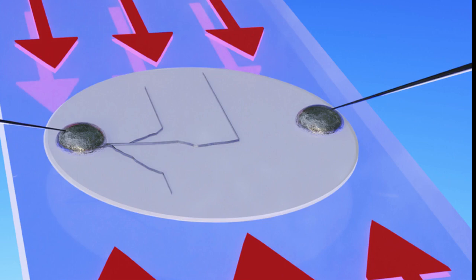In fact, a different kind of stress, called stack pressure, is often applied to battery cells, by essentially squeezing the material in the direction perpendicular to the battery's plates, somewhat like compressing a sandwich by putting a weight on top of it. It was thought that this might help prevent the layers from separating. But the experiments have now demonstrated that pressure in that direction actually exacerbates dendrite formation. The researchers showed that this type of stack pressure actually accelerates dendrite-induced failure.